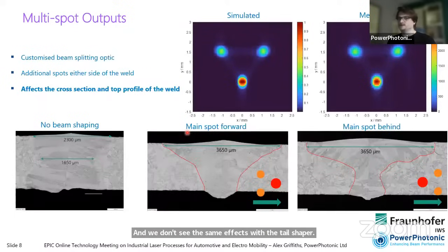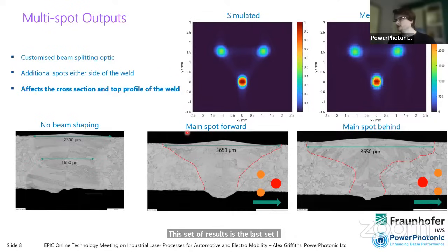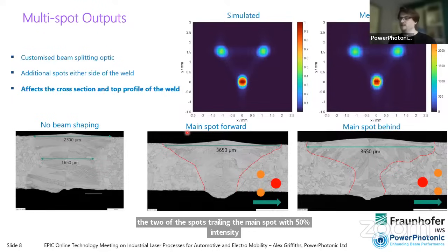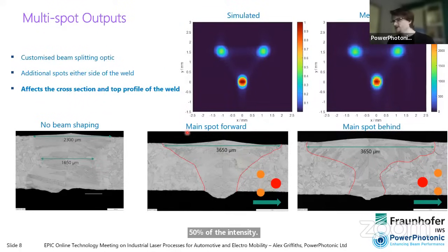This set of results is our last set I have today. This is a customized beam splitting optic that we developed, where we've aimed to have a 3-spot output with two of the spots trailing the main spot with 50% of the intensity, and these would be separated laterally either side of the weld.